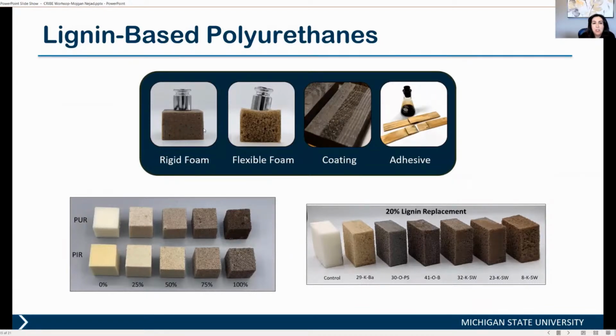We were able to do 100% replacement of petroleum-based polyol with lignin to make rigid foam for insulation spray application for housing. We could partially replace petroleum-based polyol in flexible foam applications that could be used for automotive seating, mattresses, furniture, anything that uses polyurethane foam. We have a patent where we use lignin again to replace 100% of the petroleum-based polyol to make water-based, lignin-based PUD formulations, for coatings applications. And the lignin-based polyurethane application is another project that is funded by CRIBE that we are going to scale up. I'm going to have another slide to explain that.